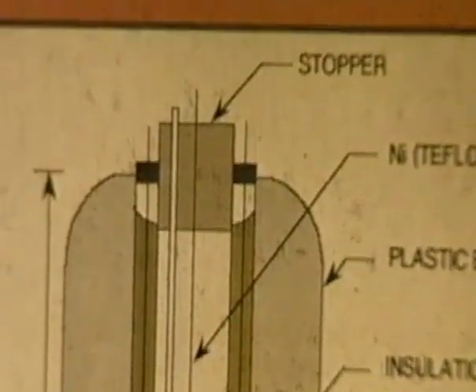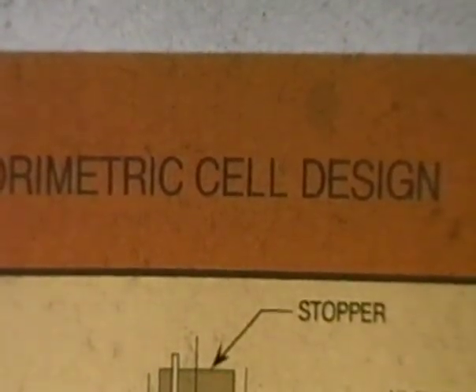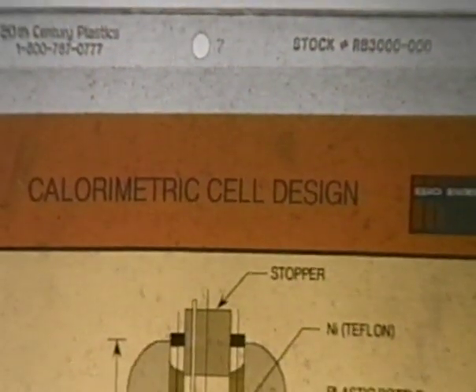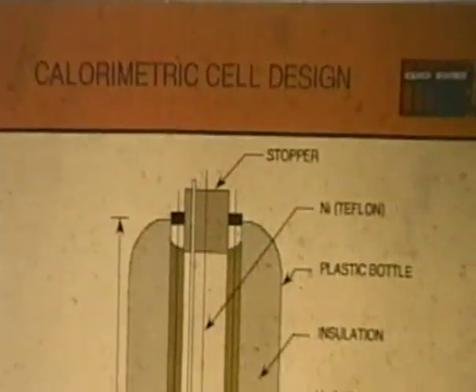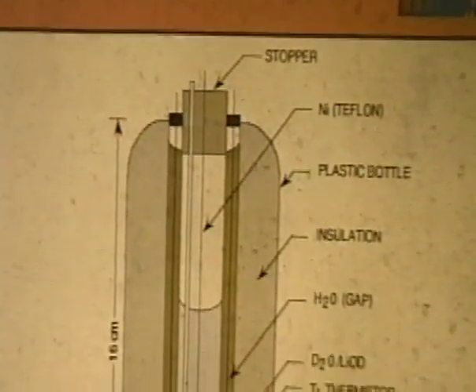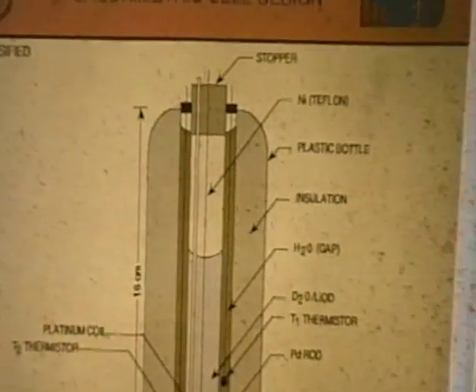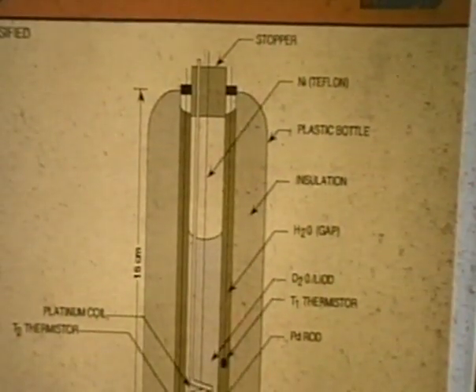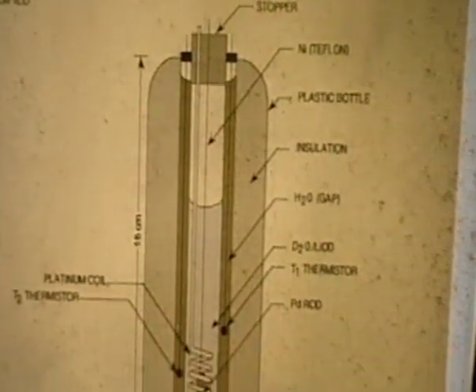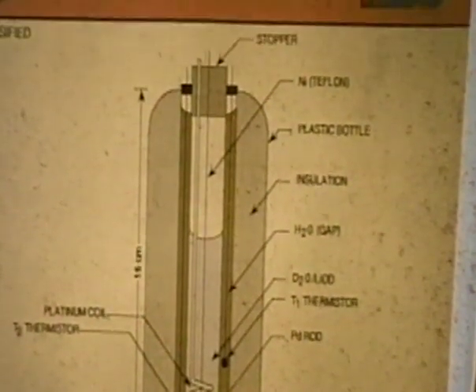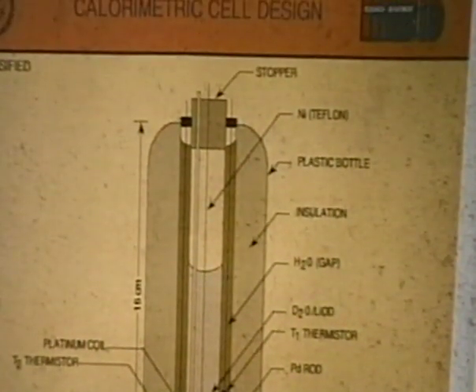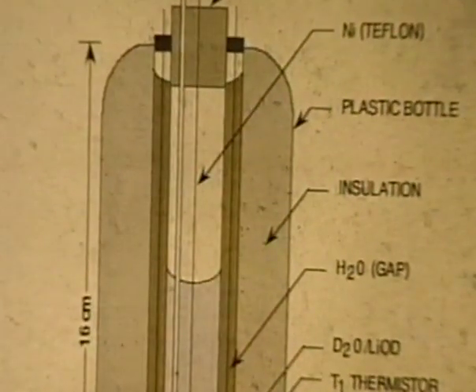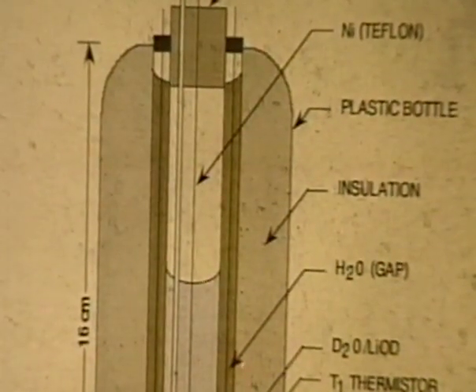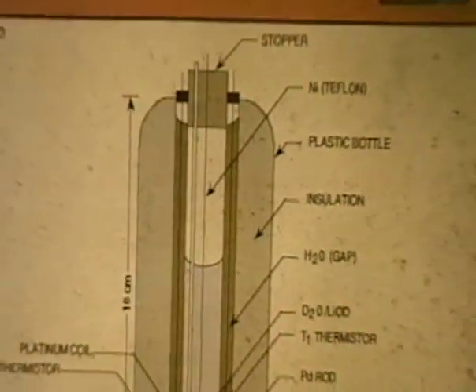The improvement we went to was using thermistors, which are much more accurate than thermometers. And we had 2 thermistors at 2 different levels. So this is a better design. We measure temperature at 2 different places on different sides of the cell at 2 different levels with 2 thermistors. Again, we have this large liquid volume, 60 cc's outside and about 18 cc's inside. So there's only a slight sensitivity to the liquid level in this design.